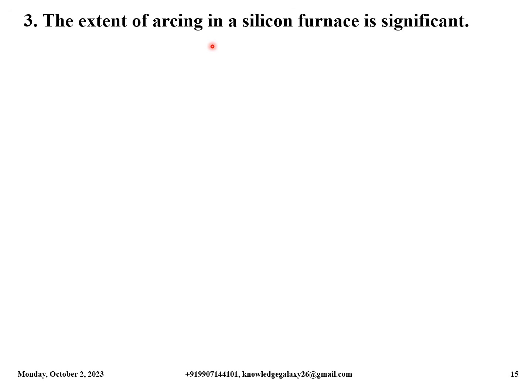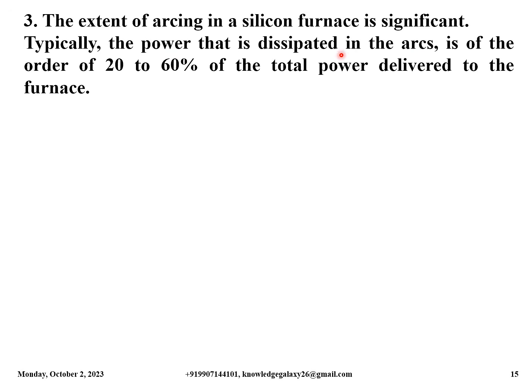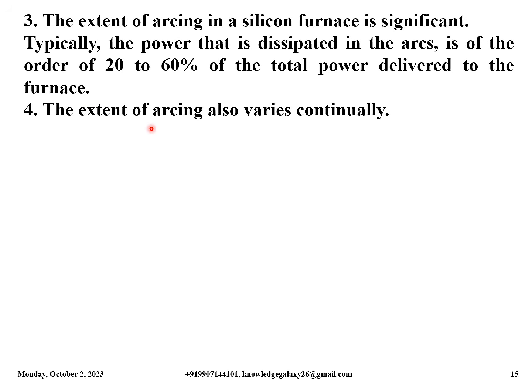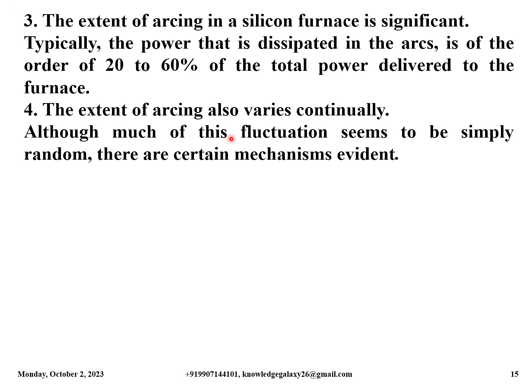Third, the extent of arcing in a silicon furnace is significant. Typically, the power that is dissipated in the arcs is of the order of 20 to 60% of the total power delivered to the furnace. Fourth, the extent of arcing also varies continually. Although much of these fluctuations seems to be simply random, there are certain mechanisms evident.